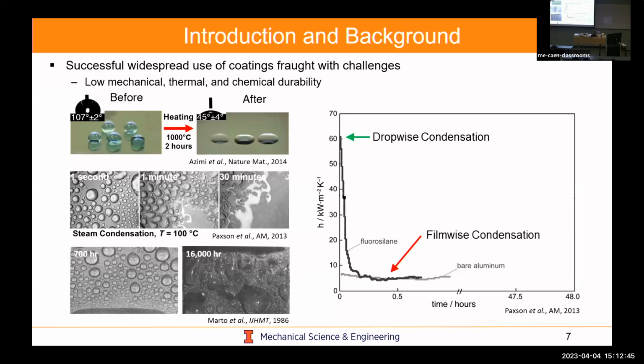And so the way you see this is if you look at a heat transfer coefficient as a function of time, you'll start great, yay, lab scale result, you go tell your advisor, but then within a half an hour, you're pretty much back to bare aluminum. And so it's no good, right? Great for Nature papers, but we'll leave this out. We'll put this in the SI. Okay. So this is a big problem, right? And we have to overcome it.